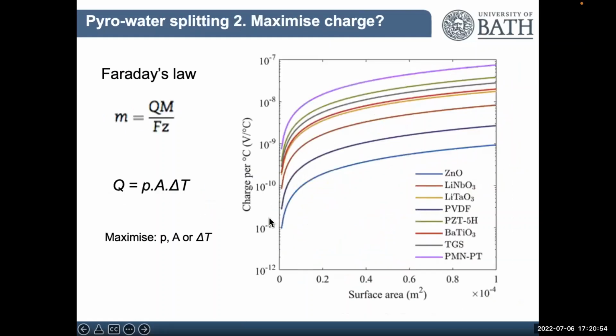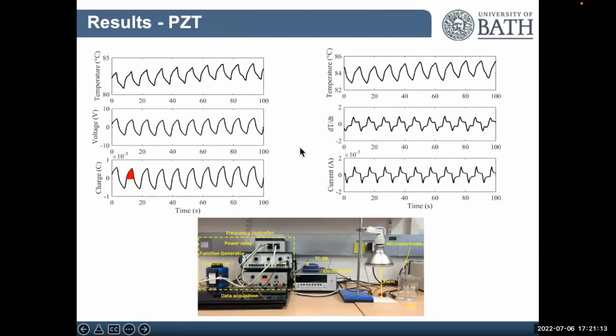For charge, it's slightly different. And the charge per degree C against area, PZT was pretty good. So very good here. PMNPT is even better, but that's a single crystal material, very difficult to source in large quantities. And so I chose PZT, the ceramic, in the end, because it can develop the voltage quite easily, and really I want to maximize the charge.